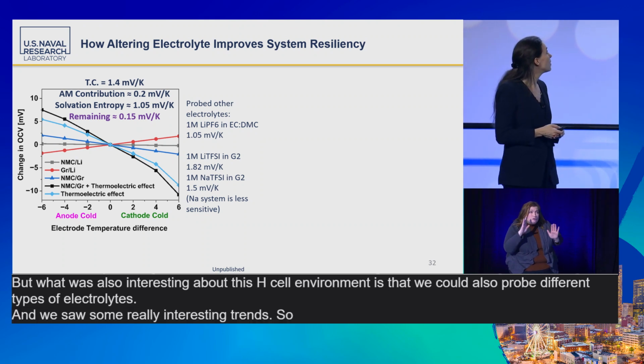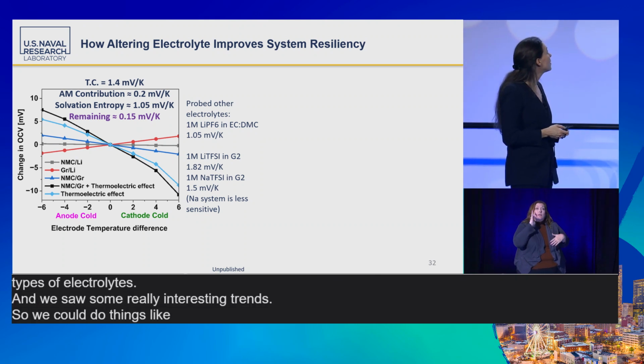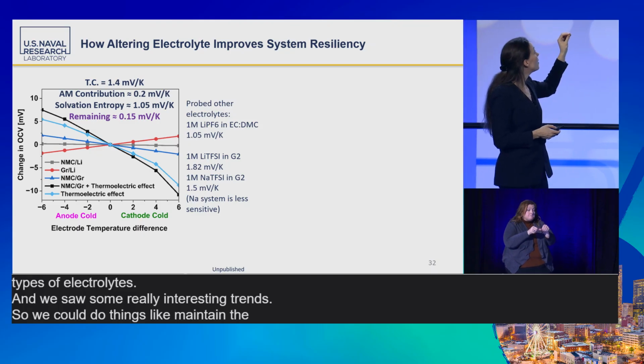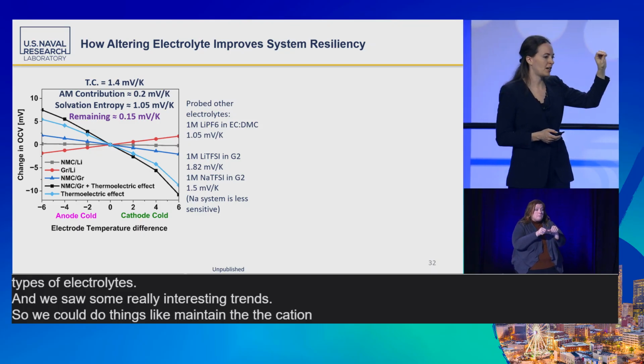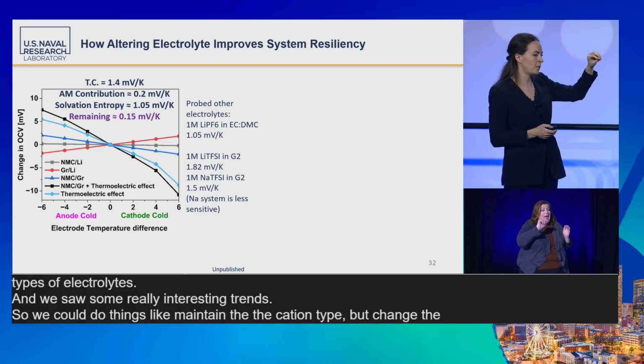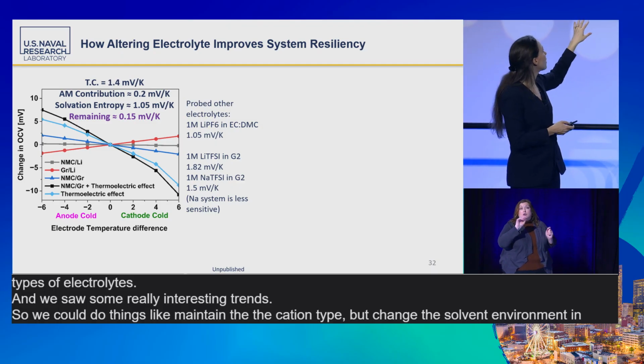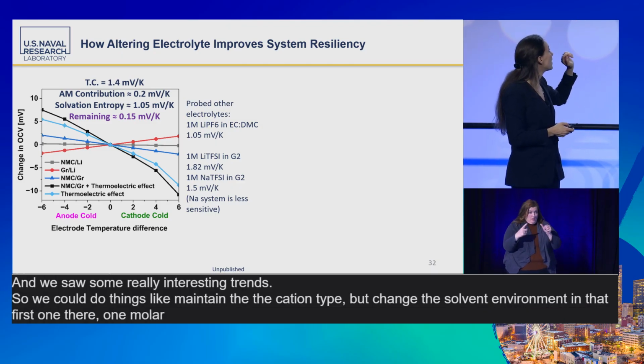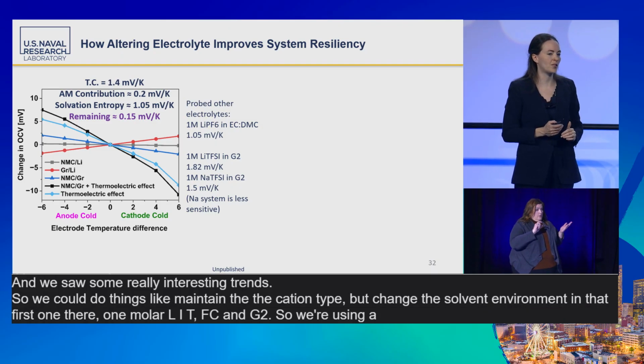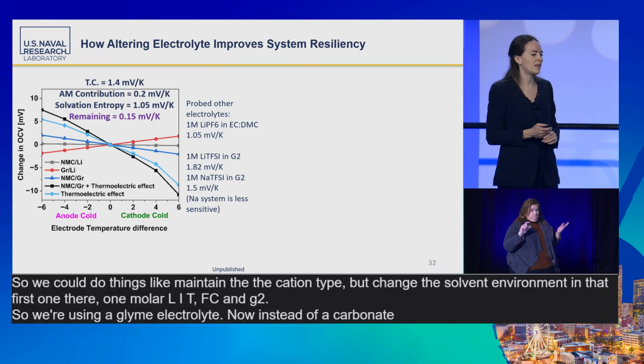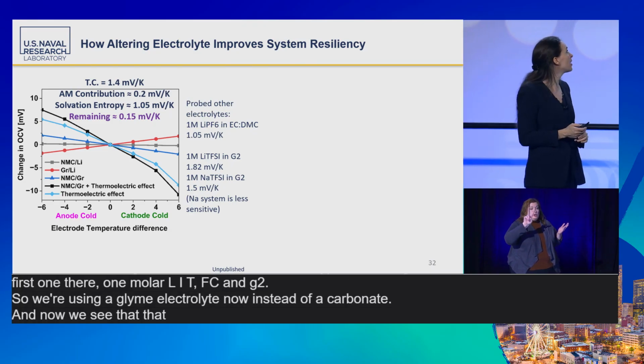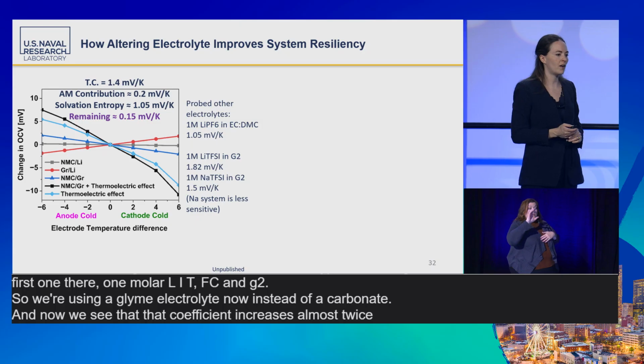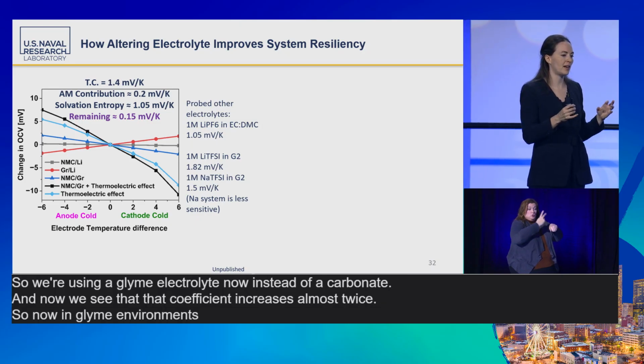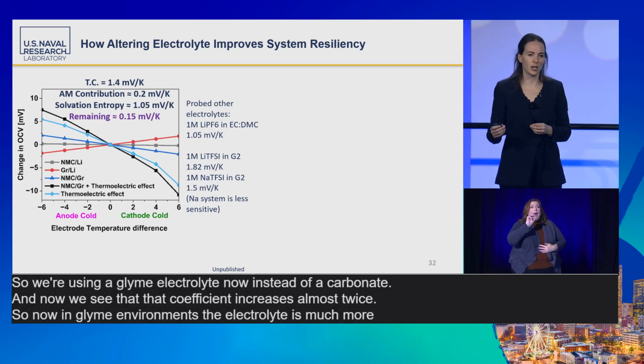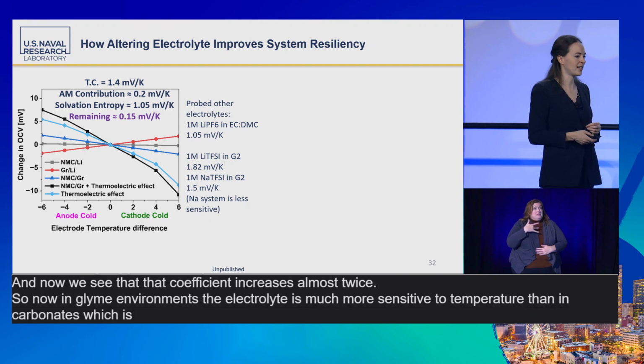So we could do things like maintain the cation type, but change the solvent environment. In that first one there, 1 molar LiTFSI and G2. So we're using a glyme electrolyte now instead of a carbonate. And now we see that coefficient increases almost twice. So now in glyme environments, the electrolyte is much more sensitive to temperature than in carbonates, which is very interesting.